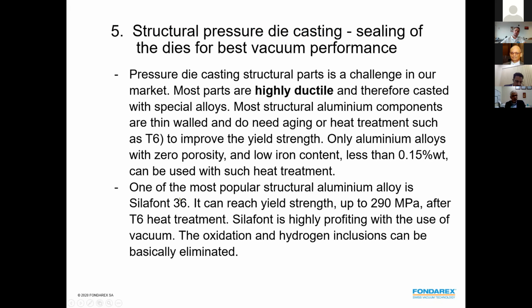Also in structural casting, most of the time we are using Silafont and some other alloys which are similar to that. They are high ductile. And of course, let's say 50 to 70% are heat treated. All of those alloys benefit in a high percentage from the vacuum. They are made to be high ductile so that they can fulfill their characteristics. Vacuum will do a very big job with those alloys. We can reach the best possible castings, which have up to a yield strength of 290 megapascal after a T6 heat treatment.